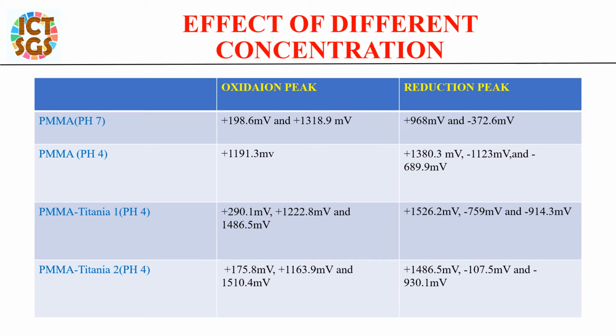Cyclic voltammogram depicts well-defined oxidation and reduction peaks observed at 100 millivolt per second at pH 4. The PMMA-Titania1 modified glassy carbon electrode has presented 3 oxidation peaks and 3 reduction peaks. The PMMA-Titania2 modified glassy carbon electrode presented 3 oxidation peaks and 3 reduction peaks. PMMA modified glassy carbon electrode shows 1 oxidation peak and 3 reduction peaks at pH 4. At pH 7 buffer solution, PMMA modified glassy carbon electrode shows 2 oxidation peaks and 2 reduction peaks.